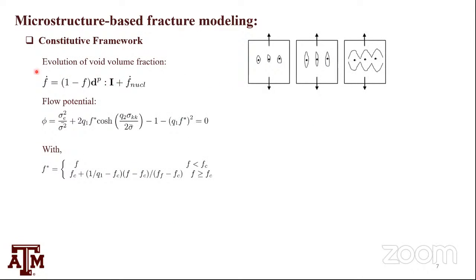The void volume fraction, the first part of this equation follows mass conservation. Then I have a second part introduced, the part of work by Chu and Needleman that introduced nucleation of voids. So you have this discrete microstructure feature that nucleates voids, and these voids grow. This gives you an early jump in the voids, and the further growth of them follows this mass conservation. The flow potential, as was written by Gurson, is here with the q's introduced by Viggo Tvergaard. And this last part is what makes fracture possible from these models. What we have is that this depends not on f directly, but on a pseudo function f star, which is simply the void volume fraction coming from growth and nucleation. But nucleation in a way violates the mass conservation, but let's keep it there.